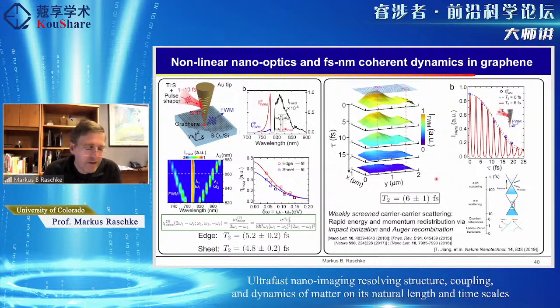And this, to some extent, was initially surprising because people had hoped that there would be very long-lived coherence in graphene, simply inspired by many other unique optical properties of graphene, especially the strong nonlinear response, which would indicate maybe there is very long coherence. But the carrier scattering in graphene is very weakly screened. And this is actually why you get exceptionally fast energy and momentum redistribution of these electrons through a number of processes, such as impact ionization or Auger recombination, which gives rise to this extremely fast decoherence.